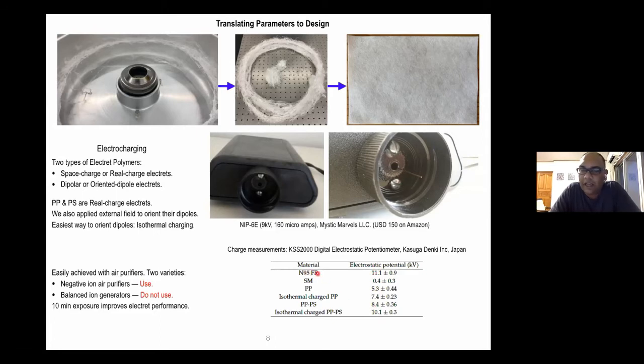So for the N95 facepiece respirator, we measured about 11.1 kilovolts at between 50 to 100 millimeter distance from the sensor. SM is for a surgical mask, the standard surgical mask that you would find in a store. This one is also made from non-woven polymer fabrics, but they're not so electrocharged. They have very weak electrocharge characteristics.